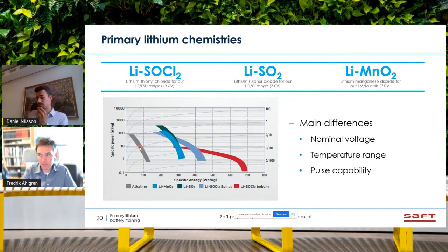I actually had the opportunity to work on a project that was implementing a very small radar system, but it was still a radar, and they wanted to have a battery on this. Even though it was quite small, the radar was still quite power consuming. You could see that the first type of cells that they tested was actually not very well suited, because the radar had quite a high power peak. The chemistry was not well suited for these peaks, because as soon as the power peak came, the voltage in the cell dropped quite substantially. When the voltage dropped, the system cut off. So they never managed to get a good reading until they switched chemistry in their cell. And this, of course, took some time until they understood exactly what was happening.